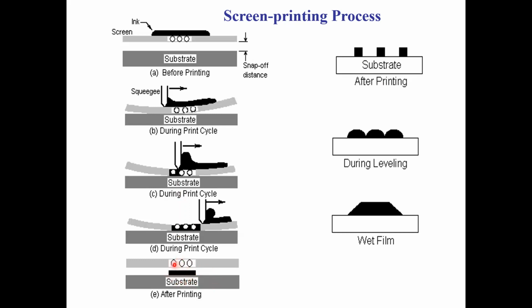If you take actually a closer look, and I'm exaggerating here, but it's not going to be continuous immediately after printing. So you'll basically have dots. Then these dots have to connect. So you need the viscosity in a range for some time after printing so that you get lateral motion to connect the dots. And eventually the driving force for making a kind of uniform film is to decrease the surface area. So we will get a film, wet film, that will look something like this.